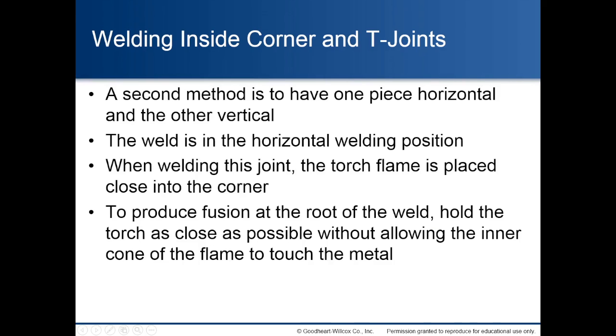Welding inside corner and T-joints. A second method is to have one piece horizontal and the other vertical. The weld is in the horizontal welding position. When welding this joint, the torch flame is placed close into the corner. To produce fusion at the root of the weld, hold the torch as close as possible without allowing the inner cone of the flame to touch the metal.